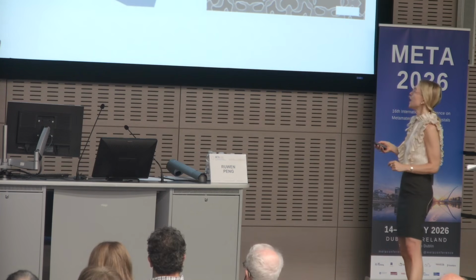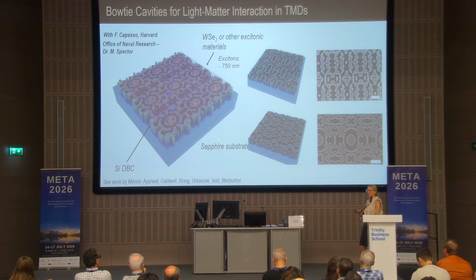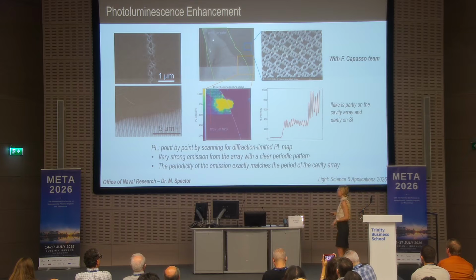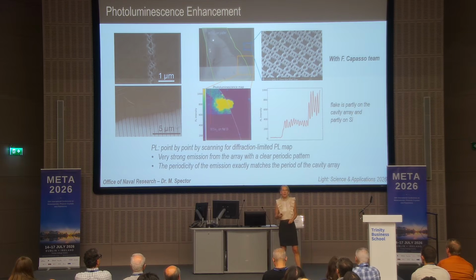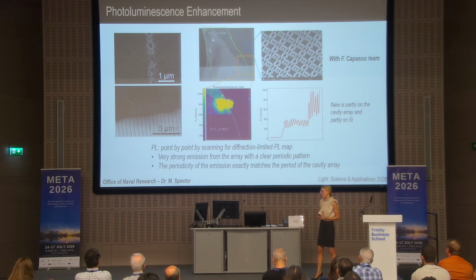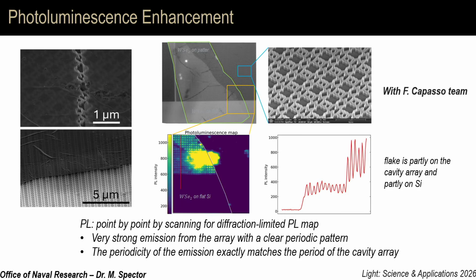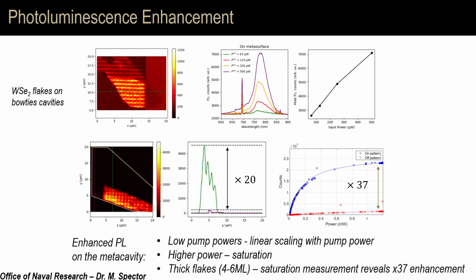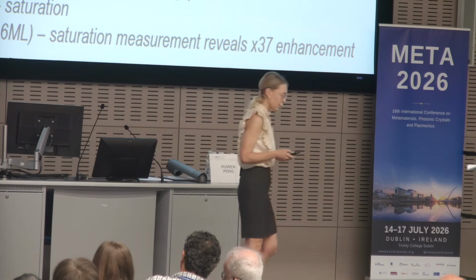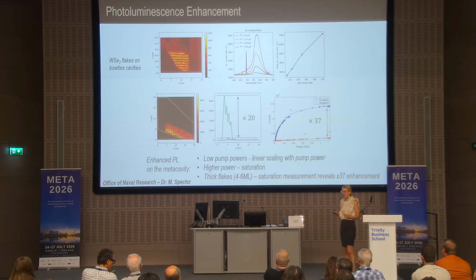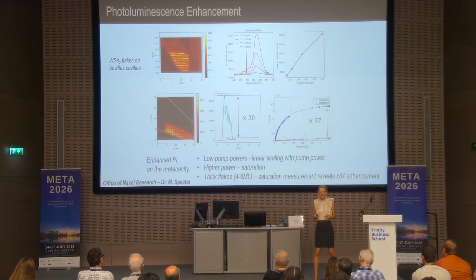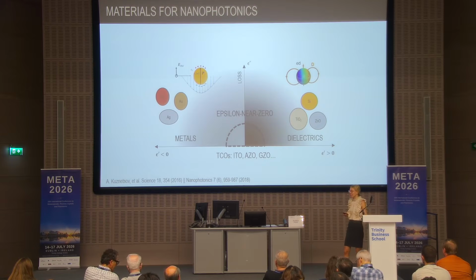I'm just flashing this very nice imaging right here to show you the power of topologically optimized structures that you can fabricate in silicon and then put a layer of 2D material on top. Not very pretty, but nonetheless, we did succeed in actually running those experiments, both in terms of very challenging fabrication of these topology optimized cavities and transferring the 2D materials and realizing the photoluminescence measurement and showing the great enhancement that is actually induced by coupling to these deeply subwavelength dielectric cavities. Again, I won't be talking much about this enhancement here, but rather want to stress again that by combining 2D material with topologically optimized cavities, we again open up new regimes of enhancing light-matter interactions.